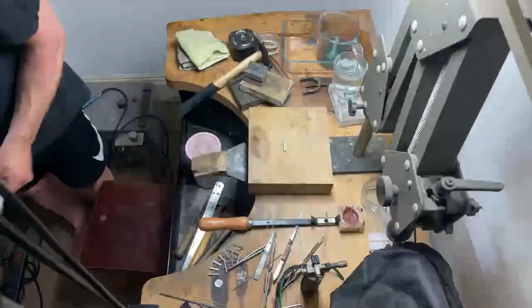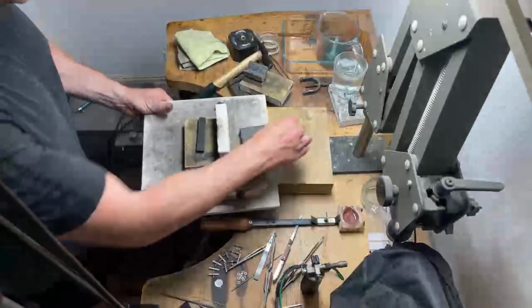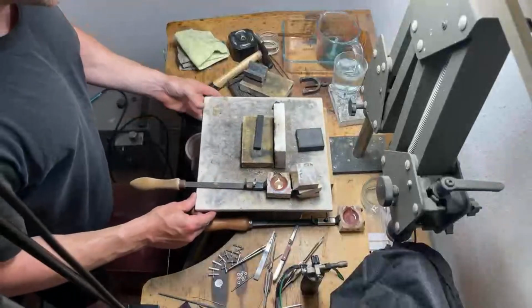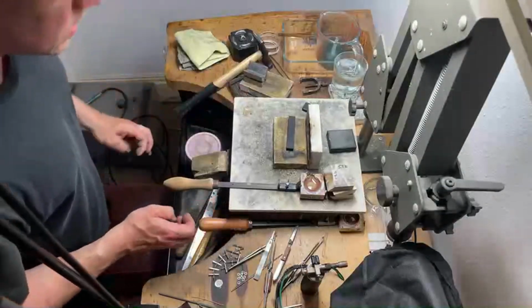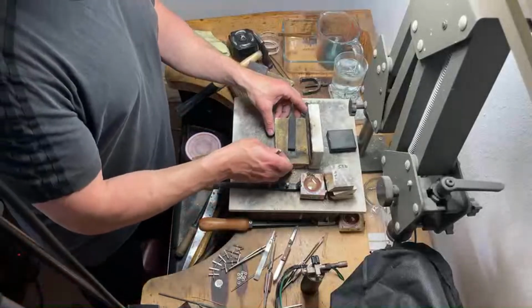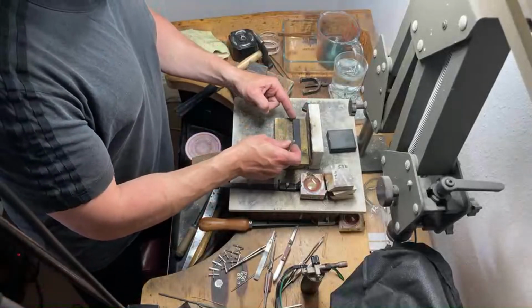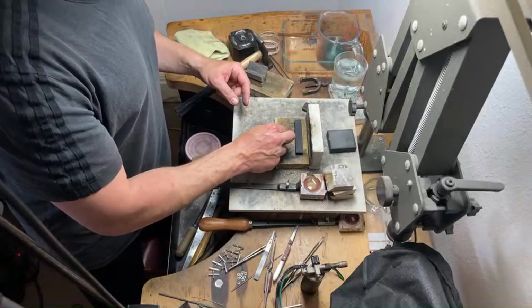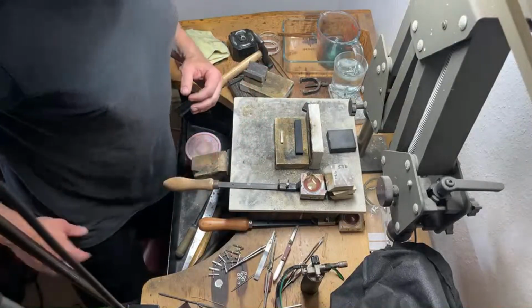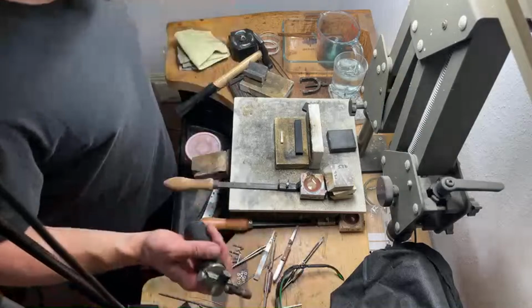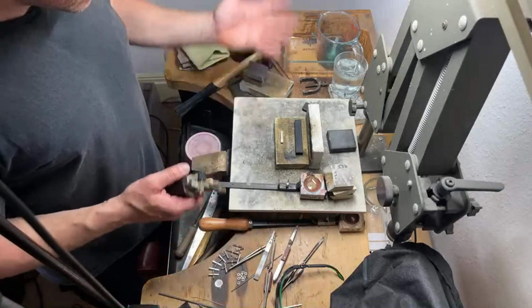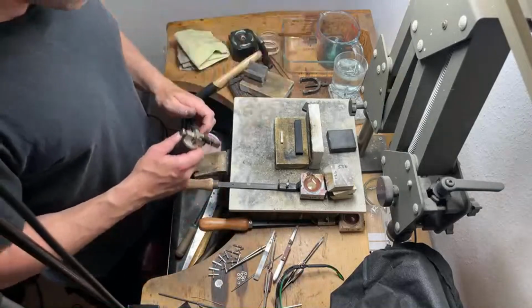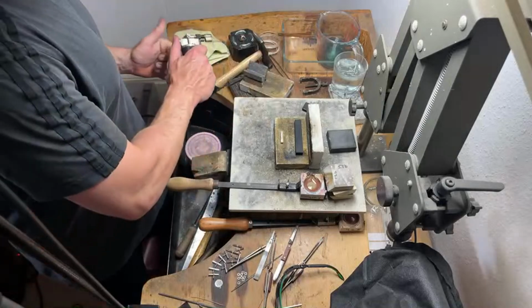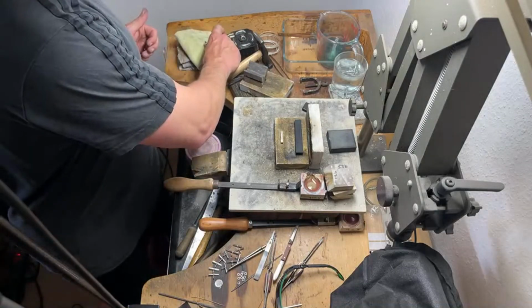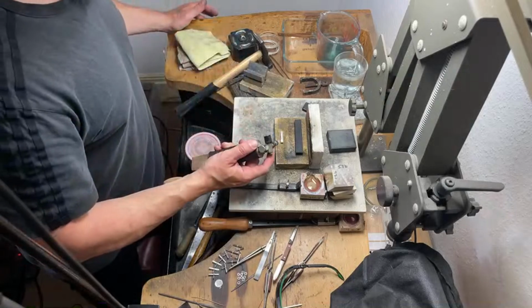With the silver, I don't quench the silver, because if you quench silver ingots, it takes on board water. And when you start rolling it out, it's like wringing out a sponge. Then where those gaps are that the water's coming out, you get porosity and cracking. But again, everyone on social media, as soon as they've melted the silver, they're dunking it in water. So that's why I'm saying they're definitely not getting usable metal doing that. Some usable metal, most usable metal, but not all of it.